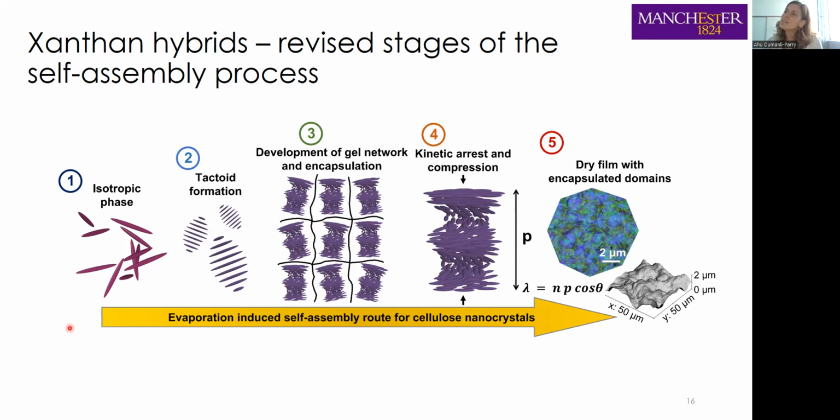So we still have the similar phases, but we think that we are developing a gel network that causes encapsulation of the tactoids themselves, or several pitches, maybe a few tactoids altogether merge themselves. Kinetic arrest and compression still happens, but it is encapsulated and compartmentalized, and we have a more cellular appearance of the films overall.